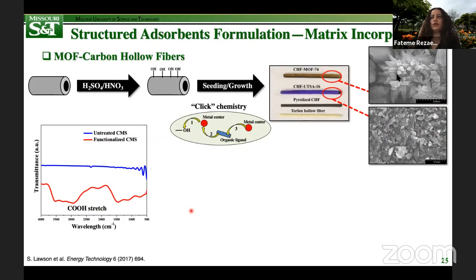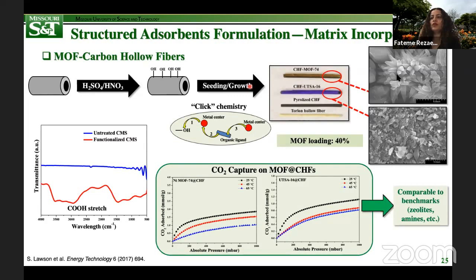But I would like to briefly discuss MOF growth on carbon hollow fibers. This is something that we also performed previously. These carbon hollow fibers required acid functionalization for growth, and therefore the fibers must be first activated with a mixture of concentrated acids to attach hydroxyl groups on the surface before MOF growth. Then the mechanism of MOF growth is based on the chemistry that is shown here, where the metal center attaches to the OH groups, followed by ligand attachment, followed by metal attachment, and so on and so forth during solvothermal synthesis to grow the MOF film. I should also mention here that these carbon hollow fibers were obtained by pyrolyzing polymeric Torlon hollow fibers.